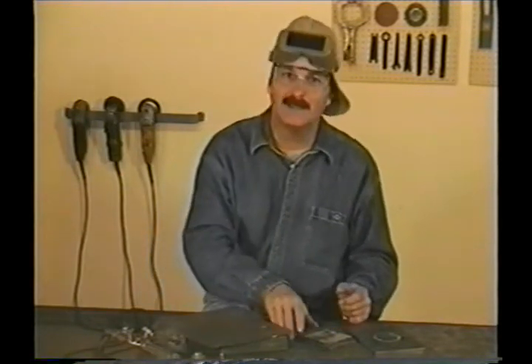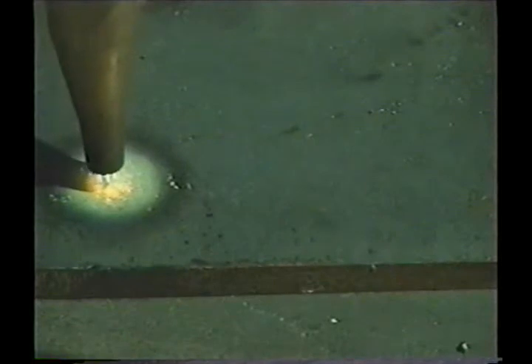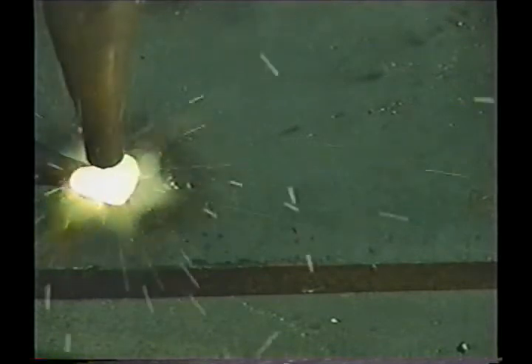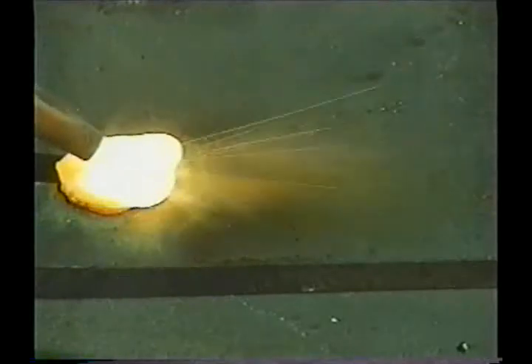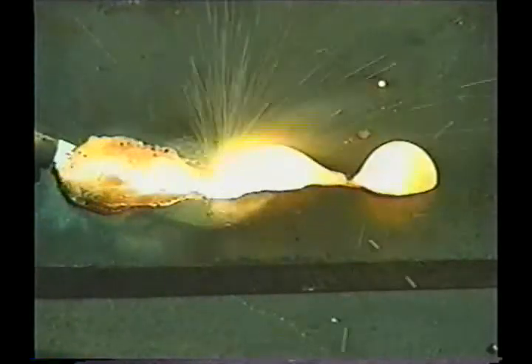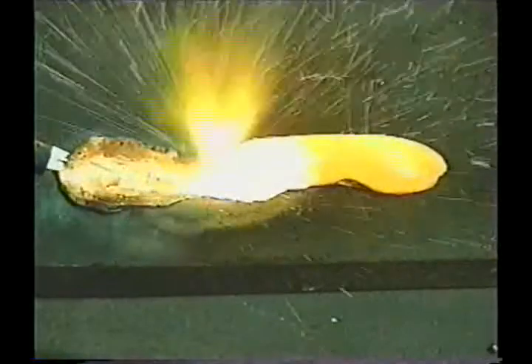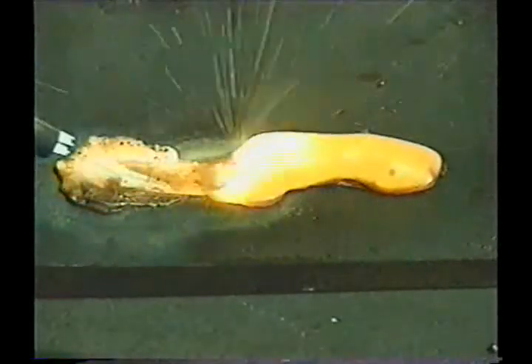If you leave that mess, when you come all the way around to finish and the cutting jet hits the cold slag, it'll probably gouge into the sides of the curve. Now, cutting torches like this don't like to cut through two pieces of metal at one time. Sometimes you'll get lucky, but most of the time, the second piece won't get hot enough, stopping the cutting jet from getting through, and the slag comes back up in the curve. The best you can do is to angle the torch and wallow through the top piece, blowing out the slag until you can preheat the bottom one. And this is never pretty.